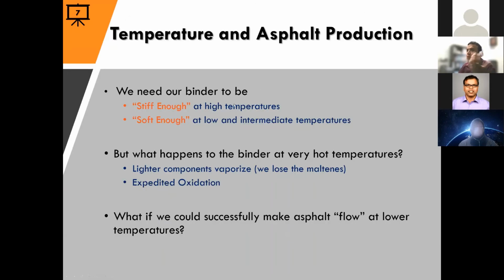Okay, so the what and why, right? Why do we even care about it? This is a group of asphalt experts, so I'm probably preaching to the choir, but you know what we want? We need our binder to be stiff enough at higher temperatures so that it's not rutting. It should be soft enough at low and intermediate temperatures so that we do not have a lot of fatigue cracking at intermediate temperatures, and thermal cracking at low temperatures.